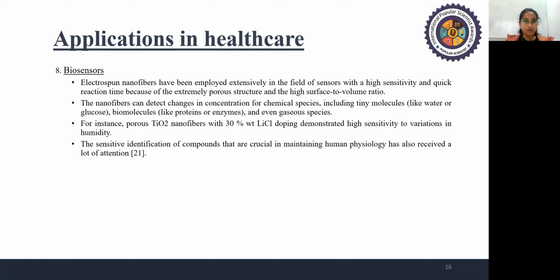So next, I'm dealing with biosensors. Electrospun nanofibers have been employed extensively in the field of sensors with high sensitivity and quick reaction time because of the extremely porous structure and high surface to volume ratio. The nanofiber can detect changes in concentration of chemical species, including tiny molecules like water, glucose molecules, and even gaseous species. For instance, porous TiO2 nanofiber with 30% lithium chloride doping demonstrated high sensitivity to variation in humidity. The sensitive identification of compounds that are crucial in maintaining human physiology has also received a lot of attention.